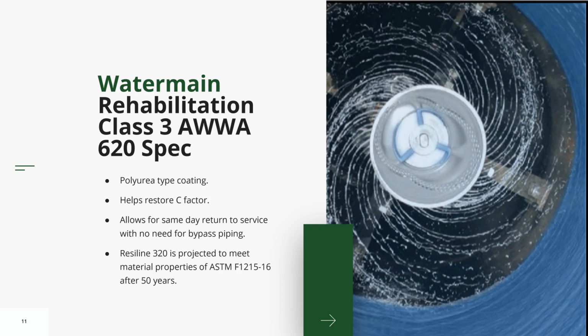It depends on the consulting engineer, the engineer of record who manages this pipeline and has the license for this water pipeline, whether they're willing to do that or not. A lot of places do it and put it back in one day and then do a boil water advisory for 3 or 4 days after that. Resiline 320 is one product that conforms with the ASTM standards here, and it's good for 50 years. So you're adding another 50 years to the life of your pipe by doing this.